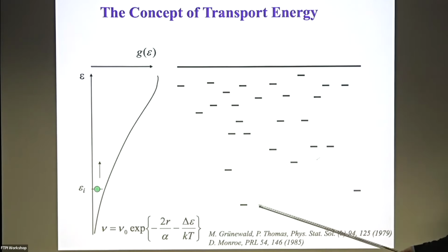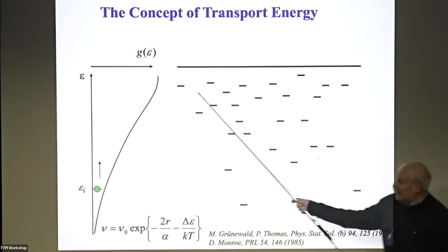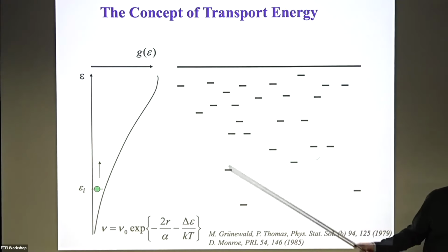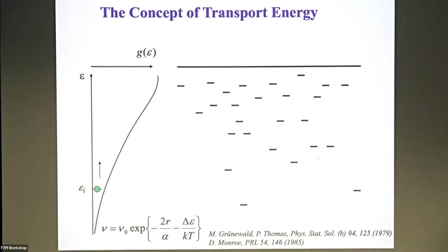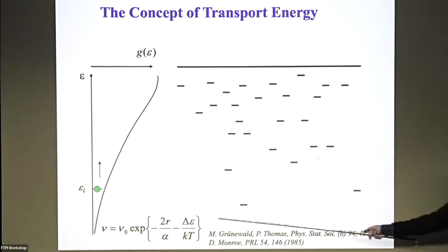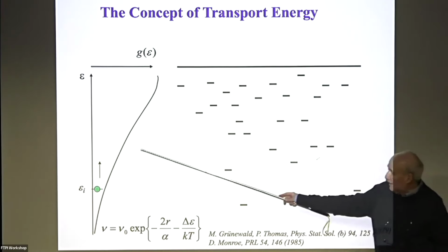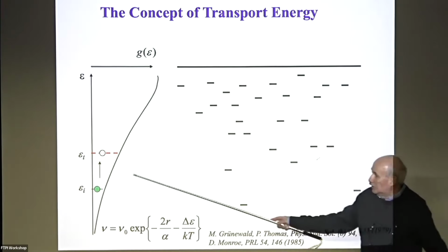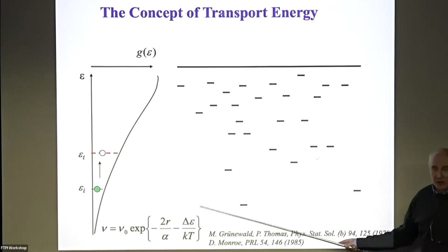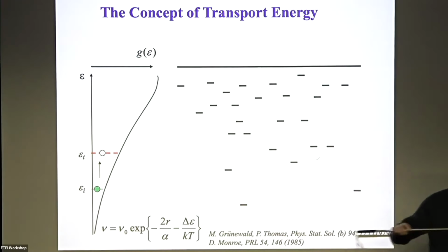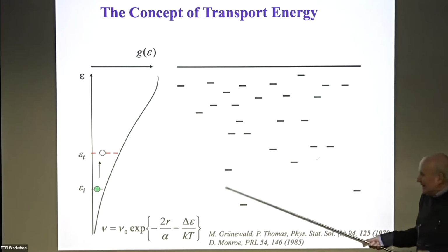used another theoretical method. It was the last idea which we learned with Boris together. We didn't develop this idea, we just borrowed it from other clever people. And I would like to show students what it means. So students, take a strongly energy dependent density of states, put the electron somewhere and ask this electron, dear electron, where do you like to go? And the electron thinks about 2 factors, space and energy, and finds the optimal target. Why not higher? Because it costs too much energy. Why not deeper? Because finally the distance is too large. So it's variable range hopping in a sense.